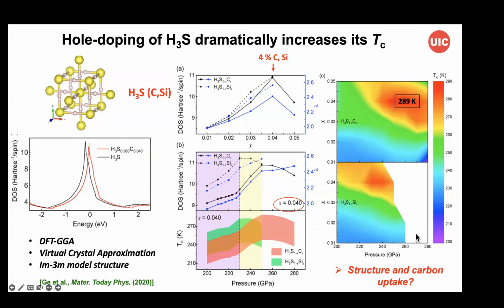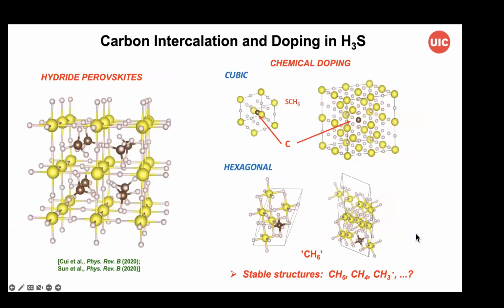But what can we say about the carbon uptake and the actual local bonding configuration of the system? Because in this virtual crystal approximation, we basically smear out all of that information in this alloy-type model. In looking at this, we built on some earlier work that was done with collaborators at Jilin, as well as Eva Zurek's group at Buffalo. We found a new class of high TC materials, the so-called hydride perovskites, where one has stoichiometric substitution of methane in the H3S lattice. It gives you very high TC.